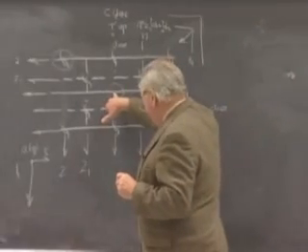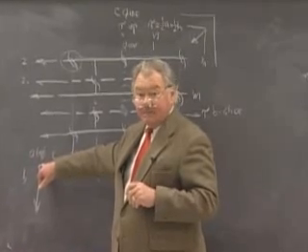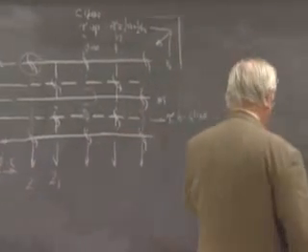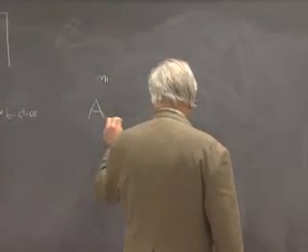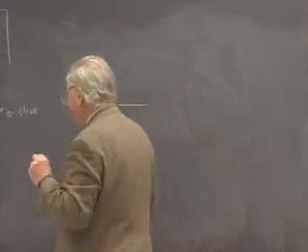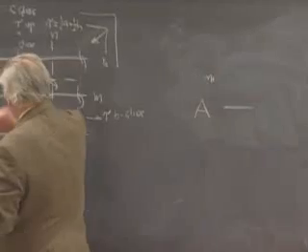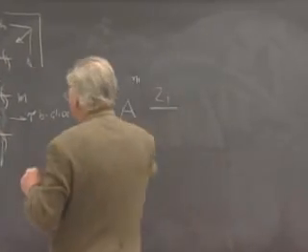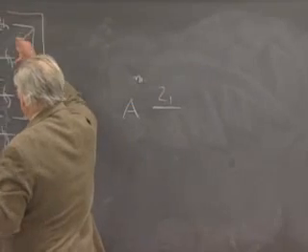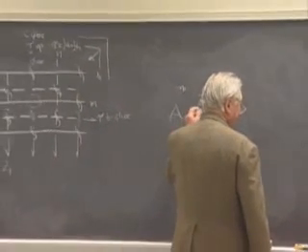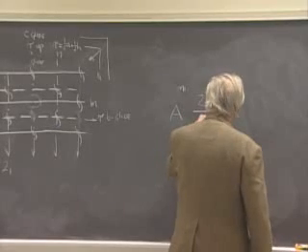First of all, the centered lattice point is now in the middle of the face out of which A comes. So this is an A lattice, side-centered A. If we look along the direction of A, all that we have for an axis is 2 sub 1. Then we have these 2 planes. One is an M, one is a diagonal glide, so that is M or N.